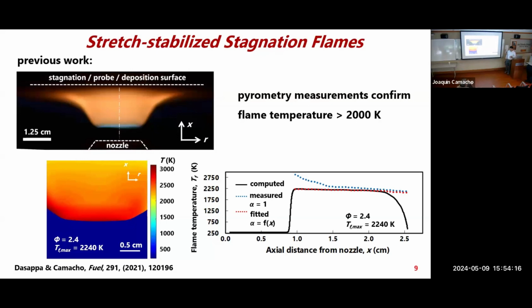Is your measured temperature appreciably higher than this? Yeah, like this 3000. I'm pretty sure these particles are not that hot. It's an optical measurement. You have to make an assumption in the black body radiation of the particle products, and a typical assumption is this dispersion coefficient here. That works okay for typical soot, but I guess this is one of our arguments that this is not typical soot. So we did an independent measurement with this assumption, and it gets us much higher.